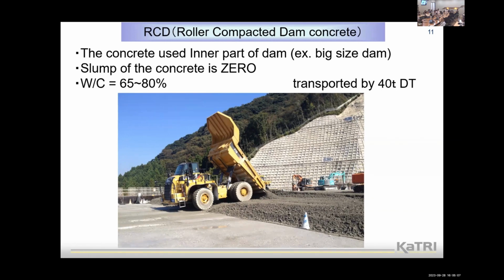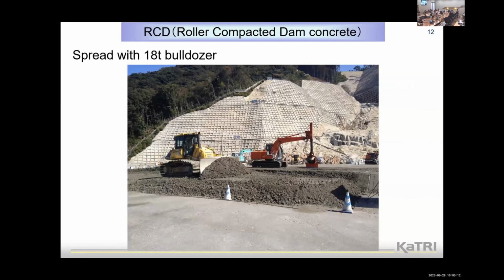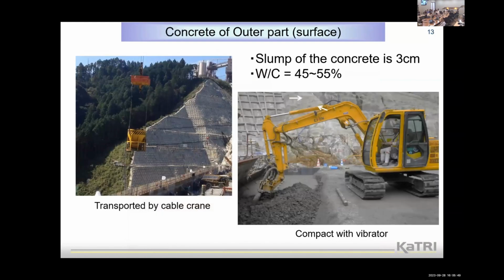So we transport it by dump truck like this, and then spread it with a bulldozer to almost 1 meter height in one layer. So many layers are spread in the dam concrete. My work site, my dam, is about 100 meters in height, so 100 layers are spread in the concrete dam. This shows the outer part, the surface area of the concrete. The slump of the concrete is 3 centimeters, and the water cement ratio is almost 45 to 55%, transported by cable crane and compacted with a very big vibrator like the right photo.